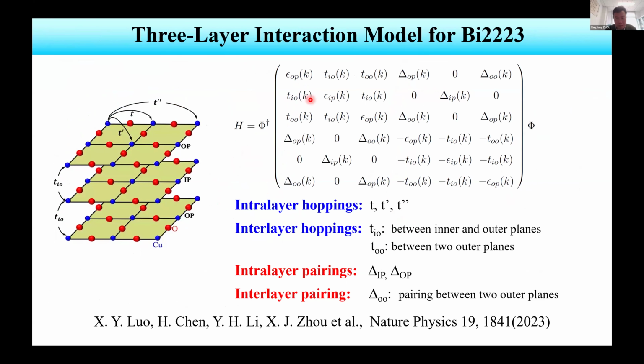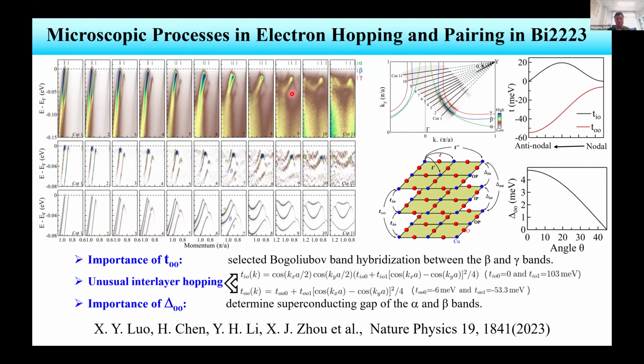For this three-layer system, we can use a three-layer interaction model to describe all the observed properties. In this model, we consider the intralayer hopping and also interlayer hopping. Interlayer hopping has two aspects: one is inner to outer, the other is outer to outer. We have TIO and TOO. We also consider the interlayer pairing, as well as intralayer pairing. By using one set of parameters, we can describe all the observed phenomena, like the Fermi surface, the band structure evolution with momentum, even the observed probability of band hybridization and the gap. So with just one set of parameters, this three-layer model describes all the observed phenomena.